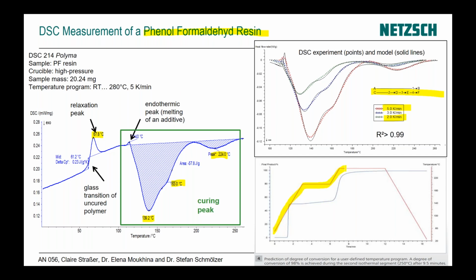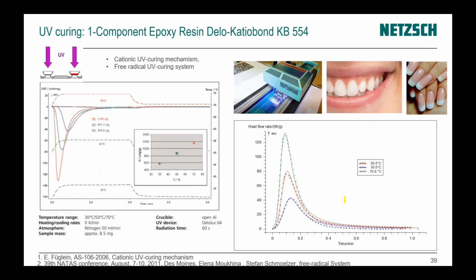Here we have a temperature profile with two isotherms, and we can see what is the degree of curing for this resin.